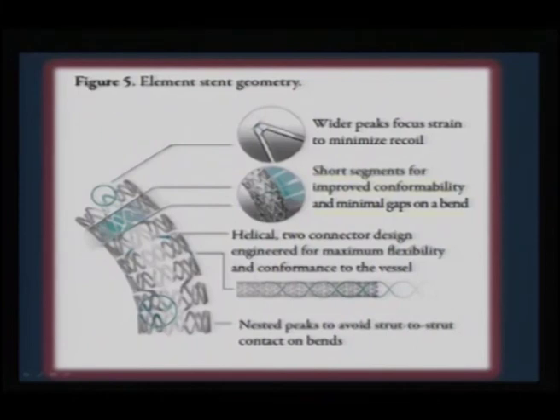When you go for short segments for improved conformability and minimal gaps on a bend, you need a design like this, because when you are trying to flip it, you should not see that strut to strut contact is made. Because you are mapping it through several regions, when bending occurs you should make sure that there is no contact, and only this sort of a helical contour will help you. And we also see this two connector design here, which is engineered for maximum flexibility and conformance to the vessel. So the design of the stent and the choice of the alloy goes hand in hand.